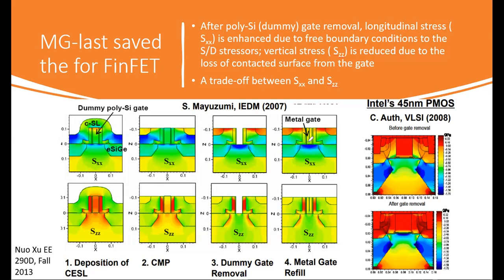You change your high-K, and then you modify your metal gate at will, then you could do a lot of jobs that you want them to do. But this process has a hidden benefit that nobody anticipated until they did it. Because of the free space exposed here, it's not strain relaxed, it's just free space that the surface silicon channel can relax into. So that means that your eSiGe can work properly. That's the beauty of high-K metal gate. It's a side benefit.